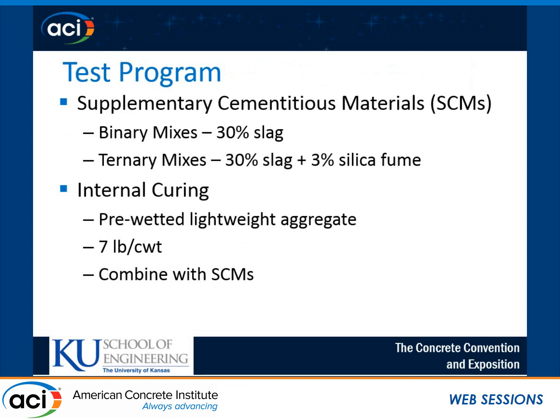For our test program that we want to compare to our control mixes, we're looking at doing a partial replacement of cement with supplementary cementitious materials. So our binary mixes are 30% slag by volume, and our ternary mixes are 30% slag and 3% silica fume. And I introduced internal curing, but again, that's with a pre-wetted pea gravel size lightweight aggregate. And we proportion this material to achieve 7 pounds per 100 pounds of cementitious material of internal curing water. And we also repeat those SCM mixes with internal curing to see if we can get a combined effect. And we do.